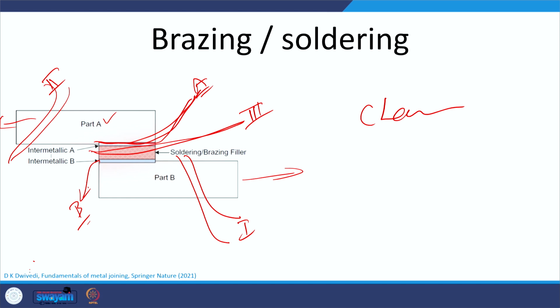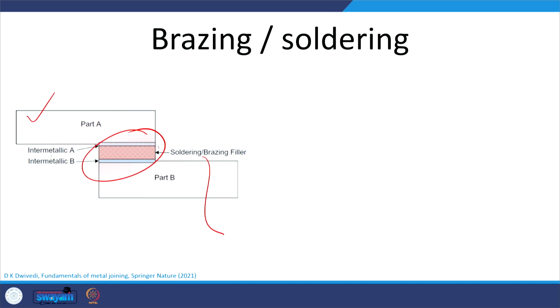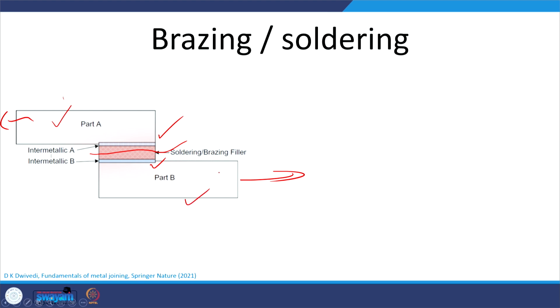So, say if the part B is failing, means the joint and the part A both are stronger. If the part A fails, which means the part B is strong, but the part A is weaker than the joint and the part B. Okay. And there is another possibility, that is if load is applied and failure occurs from the filler metal itself, then the interface is intact, both the sides, parts A and part B are intact, means they are stronger. Okay. And the filler is weak. Okay. So, by changing the filler, it will be possible to increase the joint strength, that is one of the aspects.